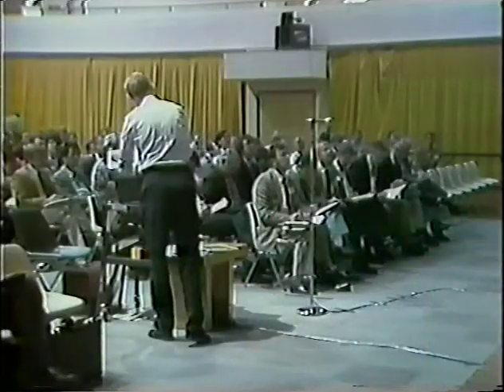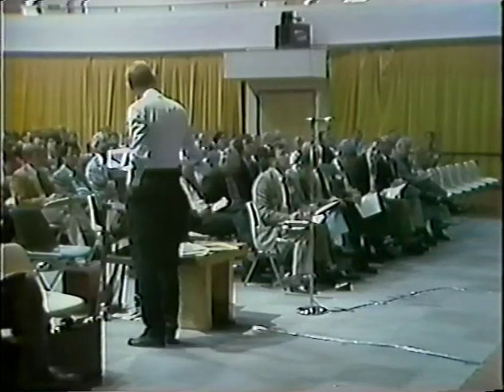The way, which is also well known, has been studied among other things by a neutron diffraction technique, is that if you, for example, increase the occupancy of the hydrogen in the metal, if you go up to a hydrogen-to-metal ratio of 1, then you get an expansion of the lattice of the order of 8% or something like that. That's well known and has been measured. And that's come out with the theory here. But it's along certain crystallographic directions that you get it. Yes. It's not uniform within the grain. It's almost like a spinodal decomposition structure you get.